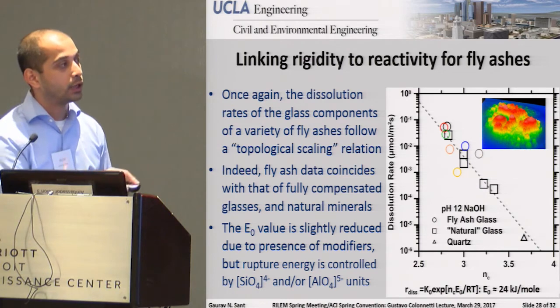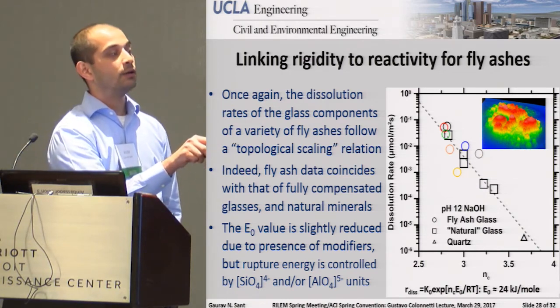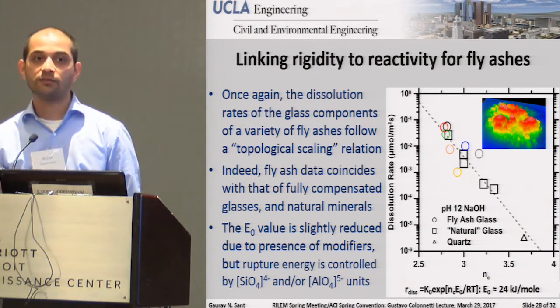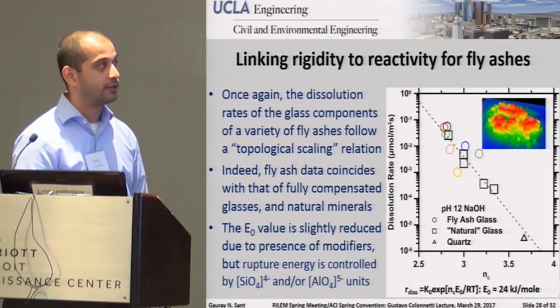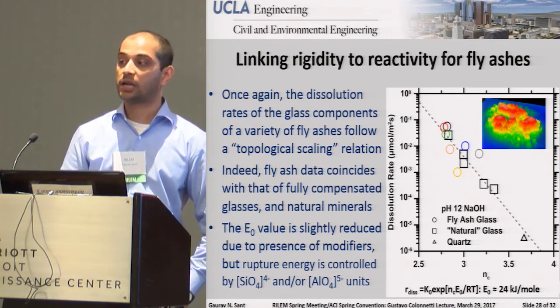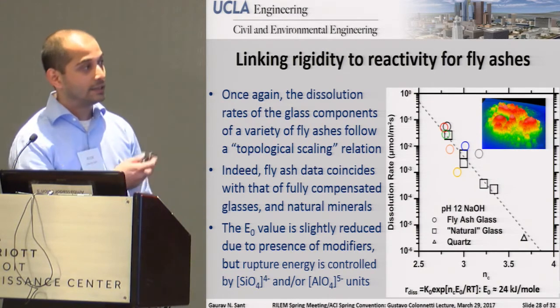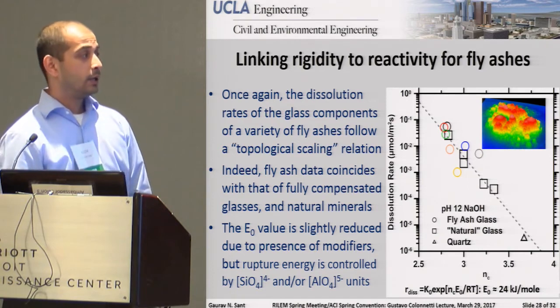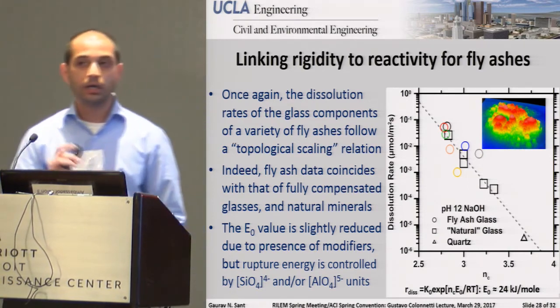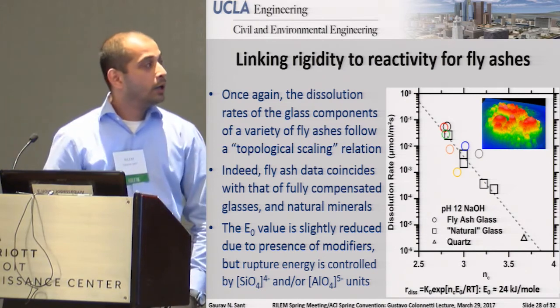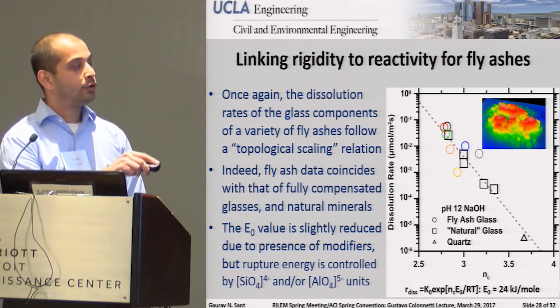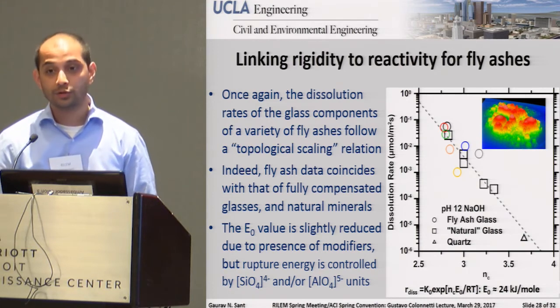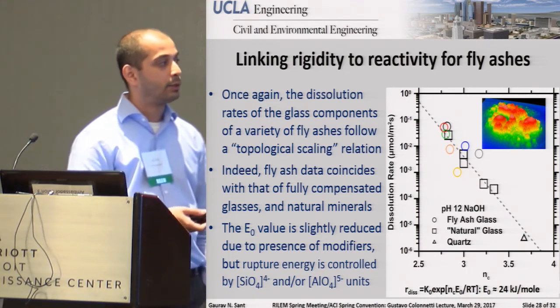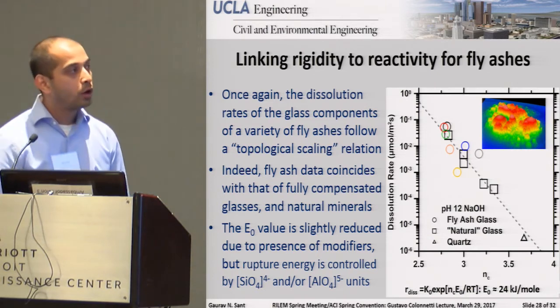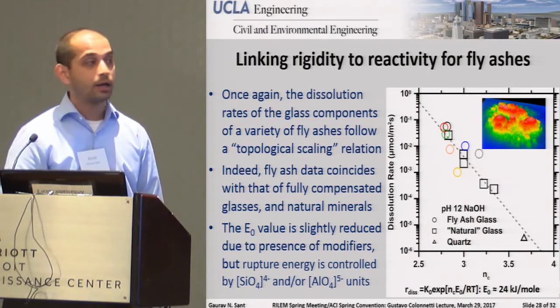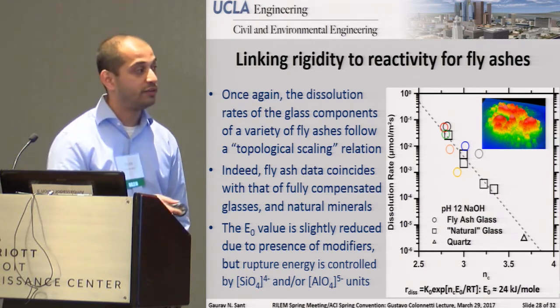Now, of course, I will point out that when you're looking at a fly ash glass, the value of E-naught drops. And that in and of itself is actually not surprising because in a fly ash glass, where you have a lot of these network modifiers, you should expect to get a slightly lower rupture energy. It should be easier to dissolve than some of these, I'm going to call them fully compensated systems. This is really quite nice because what it starts to tell you is that dominantly the E-naught value, the rupture energy, so to speak, is broadly controlled by the network silicate and aluminate structure. And that's, I think, quite an important finding because it starts to give you an indication that if you want to look at dissolution rather generically, you know what to be looking for. It's really the network features.